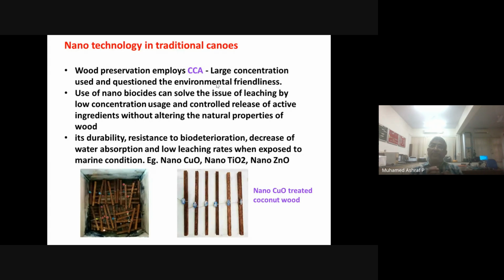The problem is that we are using a very high amount of copper, chromium, arsenic. Instead, as I told you in the beginning, nanomaterial means we can use a very small amount. So we started experiments with nano copper, chromium. Since arsenic is a little bit toxic, we are using nano copper, chromium, boron, CCB. We have done a lot of experiments and found that it works fine. The advantage is that we use very little: earlier CCA was around 7 to 8%, and here we are using 0.02 to 0.05%. That is the advantage.